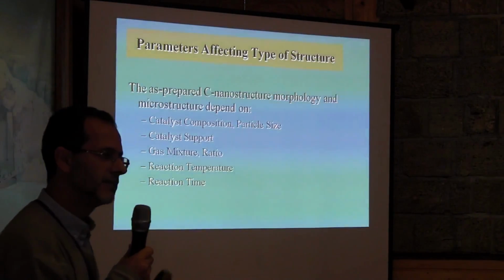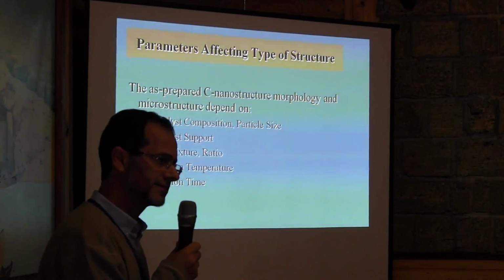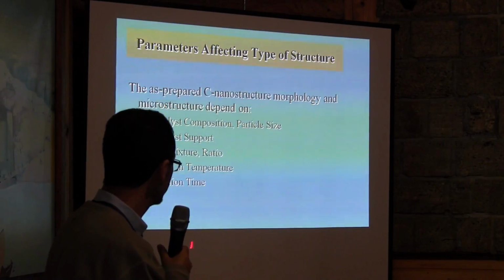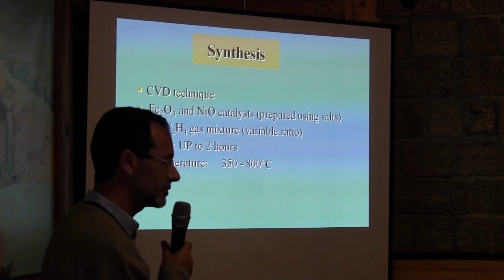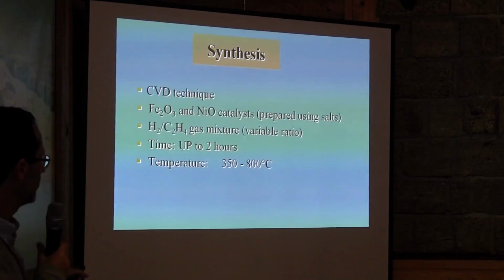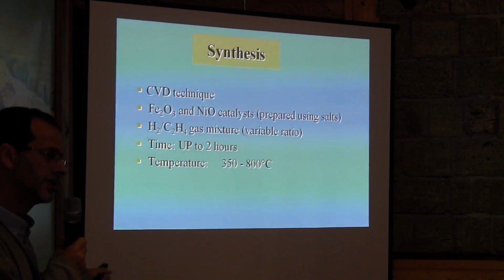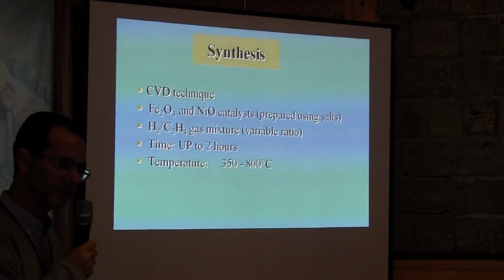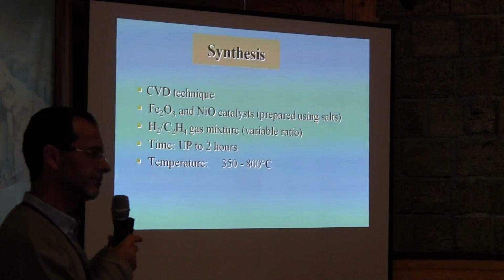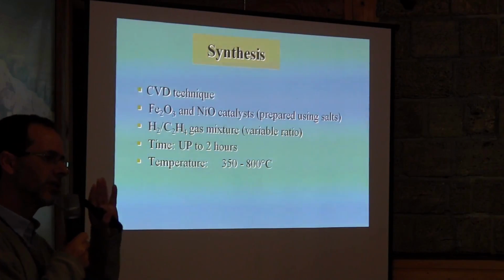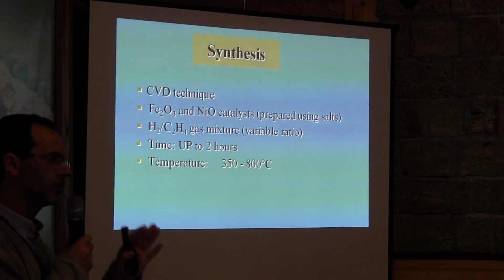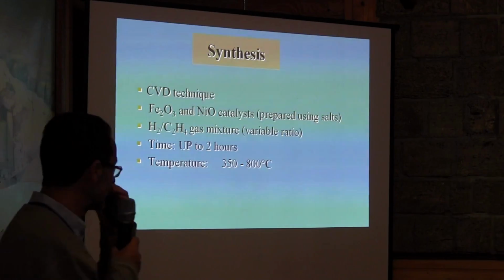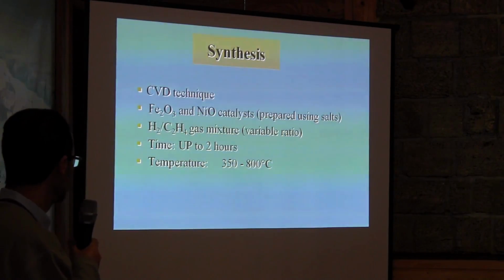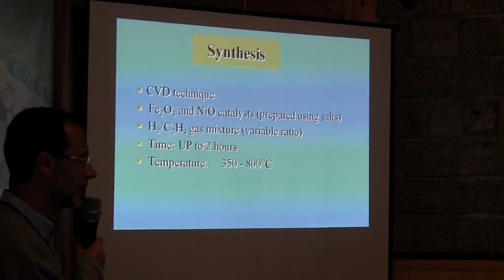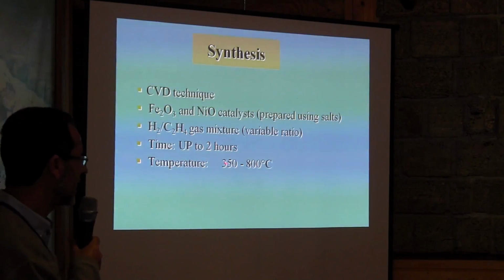So we prepare different type of carbon using different catalysts. You can see that we have different parameters to control. Next one please. So, for us, we use CVD technique, it's very simple. Then we use two types. I think we published these two papers in carbon, because maybe not the first, but we try to use oxide as catalyst, because for carbon, usually they use metal or metal alloys. So we use oxides based on metal. Then we vary the hydrogen to C2H4 ratio. We fix the time and we vary the temperature.